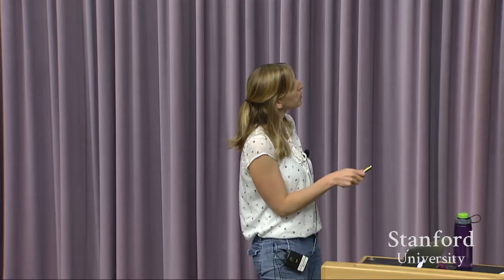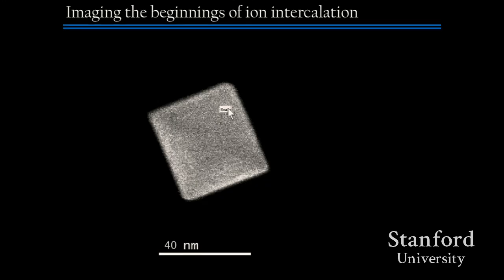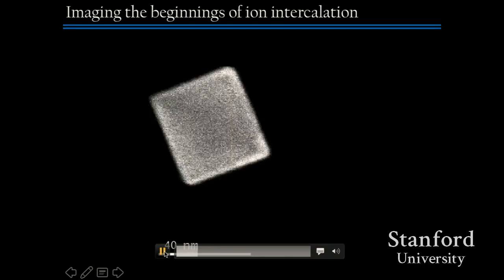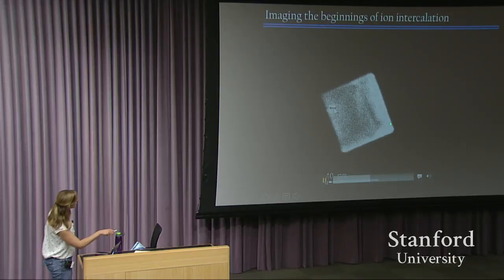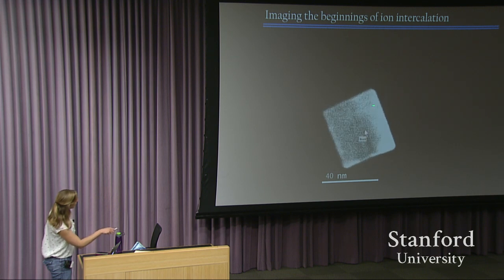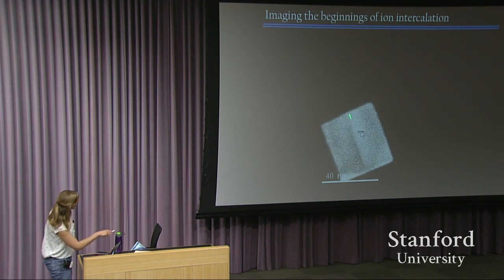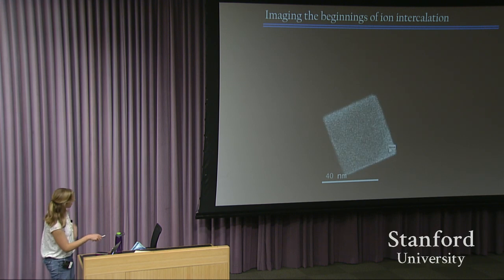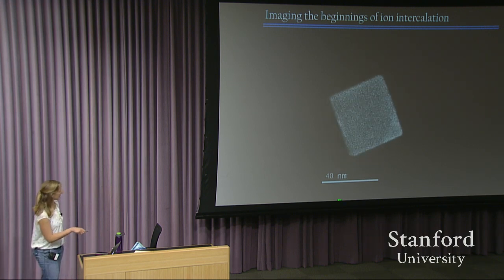Here's another movie where we wanted to image the beginnings of ion intercalation. We didn't just want to capture the process halfway through. Let me see if I can find the video to play this. So here again, white corresponds to beta, and hopefully you saw it growing in from the corners of the cube. It sprawled out to form these fingers and then eventually forms a straight phase front that moves across the nanoparticle. And then the old phase gets pushed out and then eventually the particle is fully transformed.